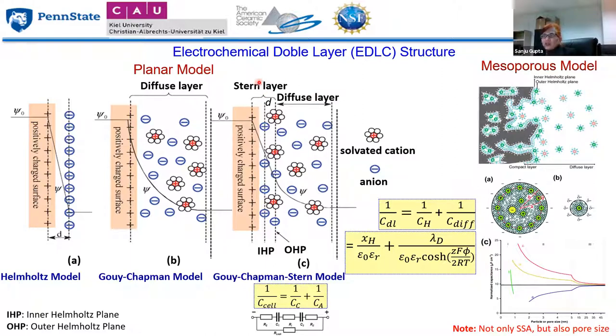So if we look at the structure of this electrochemical double layer, because everything is basically occurring, all the physico-chemical processes are taking place, at the interface of the electrode and electrolyte. The classic model was the Helmholtz model, and then it was refined by the Gouy-Chapman model, which takes into account the diffuse layer as well. And then further on, the Gouy-Chapman model was modified by Stern. So this is called the Gouy-Chapman-Stern model, according to which we have the first, or what we call the inner Helmholtz plane, and an outer Helmholtz plane. In other words, this double layer consists of these two layers and then the corresponding diffuse layer.